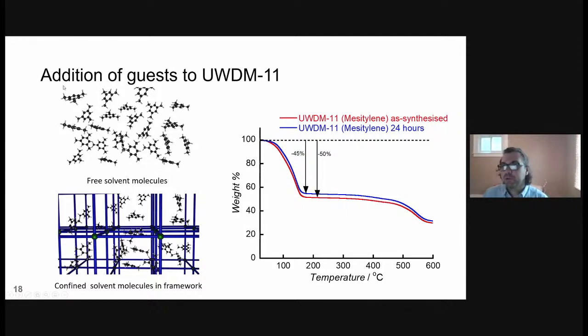So we took our solvent molecule, which is mesitylene, and loaded that into the MOF. People have shown that adding solvent molecules into the pores of the MOF, where they're confined, can result in an increased effective viscosity. People have demonstrated this with systems where they're looking at molecular rotors in MOFs. We chose mesitylene as it's retained quite nicely by the MOF. This is just a TGA, which shows we don't lose too much if we leave the MOF sitting out of the solvent, which is nice in terms of preparing a sample. We know we're not going to be losing all the guest molecules as we make up the sample for the solid state NMR.